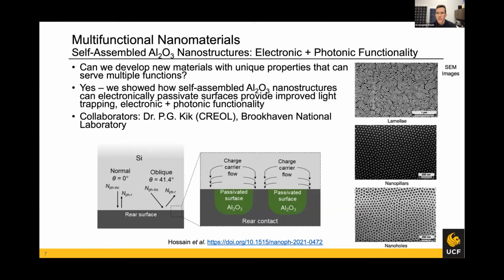In addition to these passivating carrier selective contacts, we're also interested in multifunctional materials, particularly these self-assembled nanostructured materials that can provide not just one functionality. They're not just optical in nature or electrical in nature, but they actually can provide an electronic and a photonic functionality. And so I was able to send one of my PhD students up to Brookhaven National Labs to work with a self-assembly expert, and we collaborated with Dr. Kik at CREOL to basically show how these self-assembled aluminum oxide nanostructures that can come in different forms and varieties depending on the block copolymers that are used.